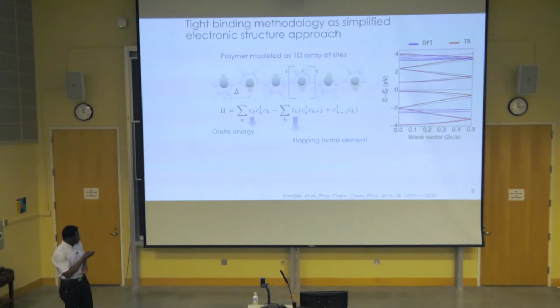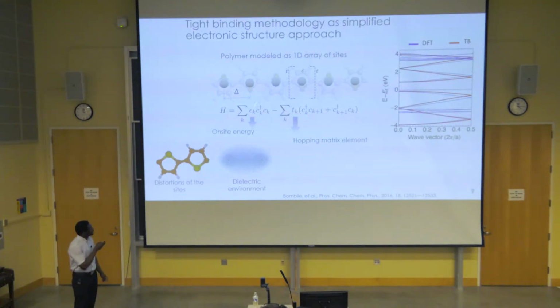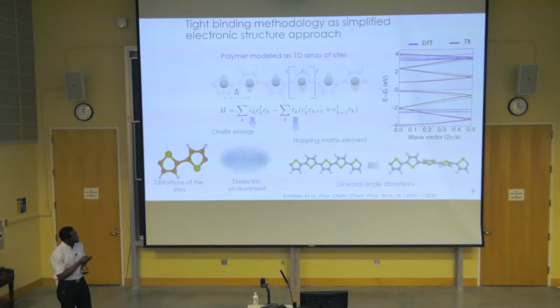And I should mention that the parameters within this tight binding model are sensitive to changes in the surrounding environment of charge carriers. The on-site energies are affected by changes or distortions of the monomer units, and also by changes in the surrounding dielectric medium. And the hopping matrix elements are affected by dihedral rotations. So this is the dihedral angle between two successive monomer units, among other factors. So over the rest of my talk, I'll show you how we use this model to investigate the localization of charge carriers and excitons.